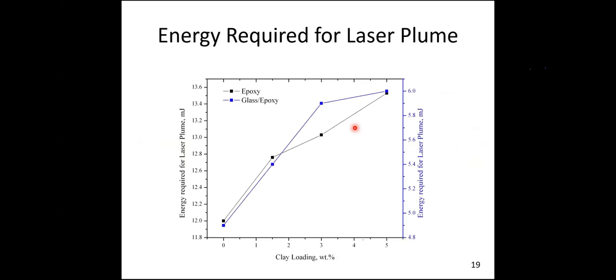So this is a small study. We wanted to understand the effect of clay. We were curious to know the energy required for the laser plume. So we have done it for two different samples. One is epoxy clay, the other one is glass epoxy clay. On the left hand side, if you see, for epoxy and glass epoxy, it requires less energy to make the laser plume, wherein if I add the clay, it needs more energy to get the laser plume. This is what we could see from this graph.